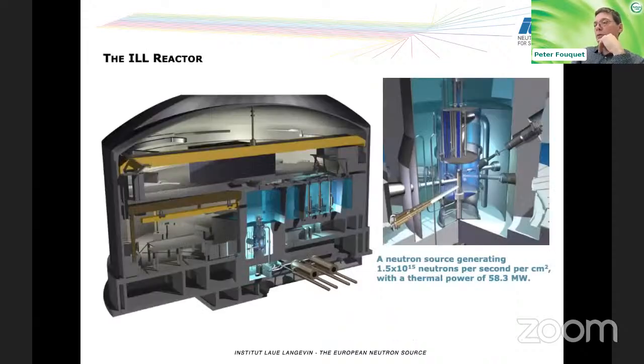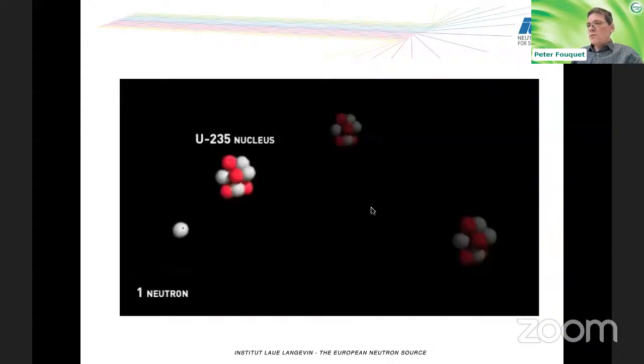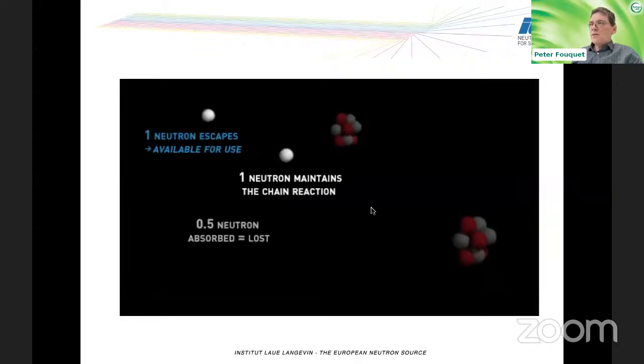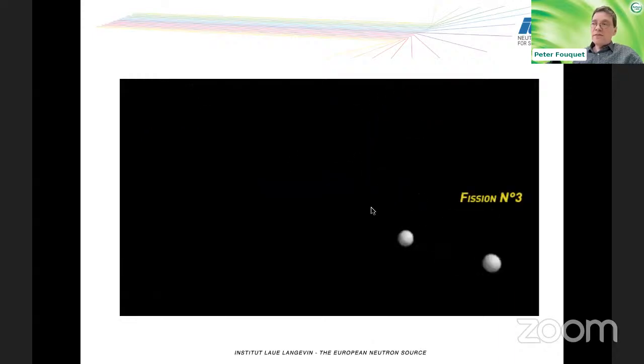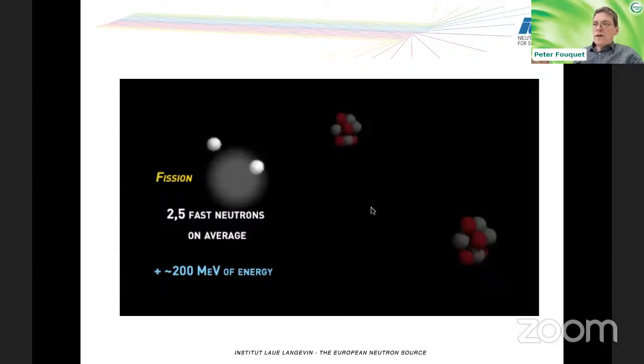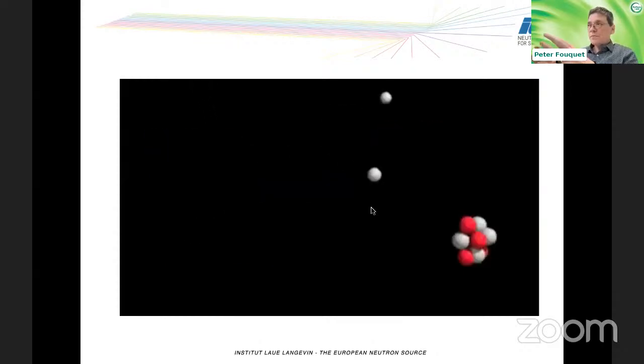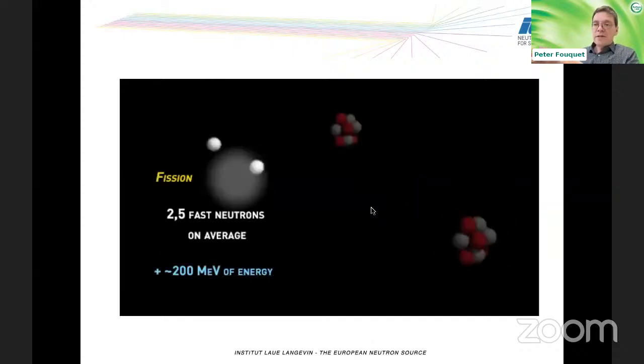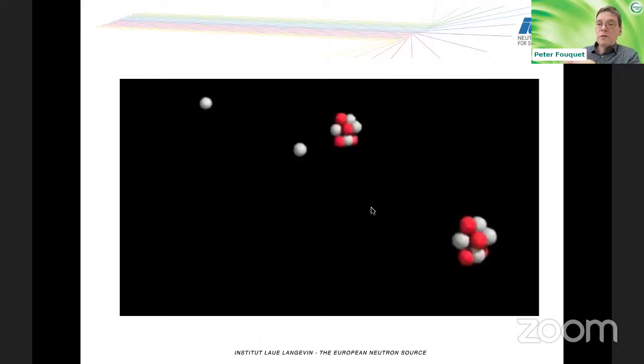Now, we produce the neutrons with a reactor at ILL. And what you can see here is a cut through the reactor building. And in the middle, we have the center of the reactor. That's where we create our neutrons with a nuclear reaction. And they are extracted around the core of the reactor with neutron guides and brought to the instruments. Now I have a little animation of first how the neutrons are created. So whenever you have a fission process, we create 2.5 fast neutrons. And these neutrons, they can partly be extracted, and part of them are used to maintain the nuclear reaction.